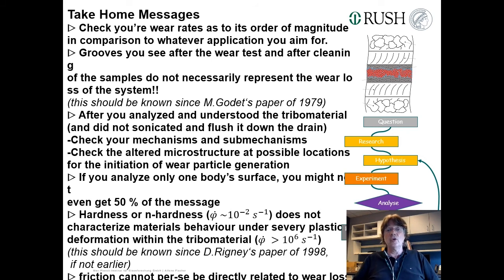So check your mechanisms and sub-mechanisms, whether they match the application you aim for, and check the altered microstructures at interesting locations for the initiation and propagation of cracks in order to generate wear particles. So if you just have nano-size wear particles in your system, so you check the tribo material, if you have micrometer-size wear particles and a very thin shear band on top here, you have to look here, because you have to optimize here, not here. You have to optimize your system down here.